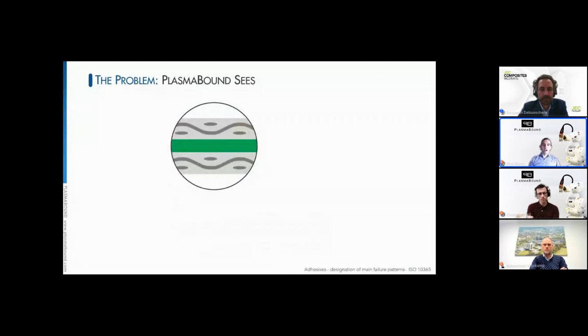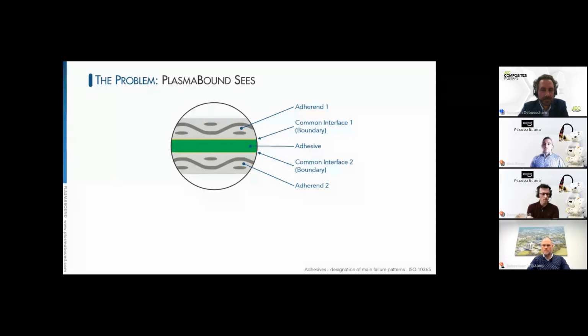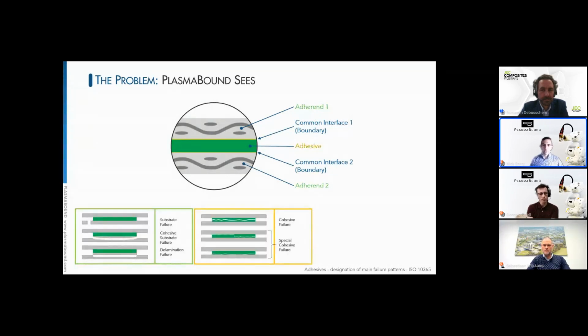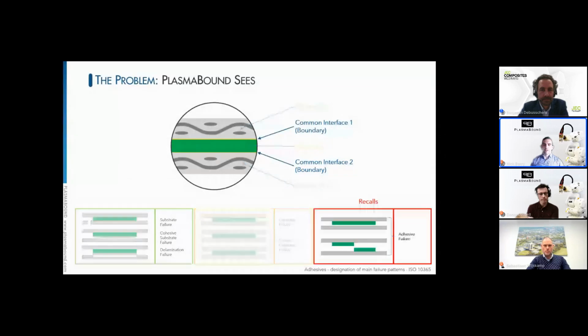However, because I'm not technically in that industry, but in a different industry, which is the industry associated with surfaces, what I see when I see a bond joint issue is typically most people will see 3 components, but in reality, I see 5. There are 2 common interfaces, and these are key in the performance of a bond joint. While substrate and cohesive failure are acceptable sources of failure, which are defined by the 3 components that everybody sees when they look at a bond joint, it is often the situation that the common interface is the reason why a recall will occur. And in the case of Tesla, it is this situation where the common interface is causing a failure. The primer is missing, and essentially the adhesive was coming away from the substrate.